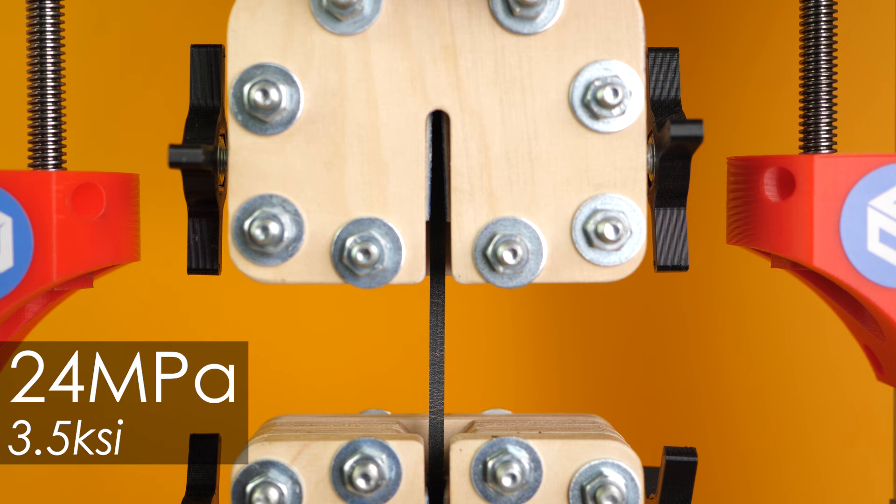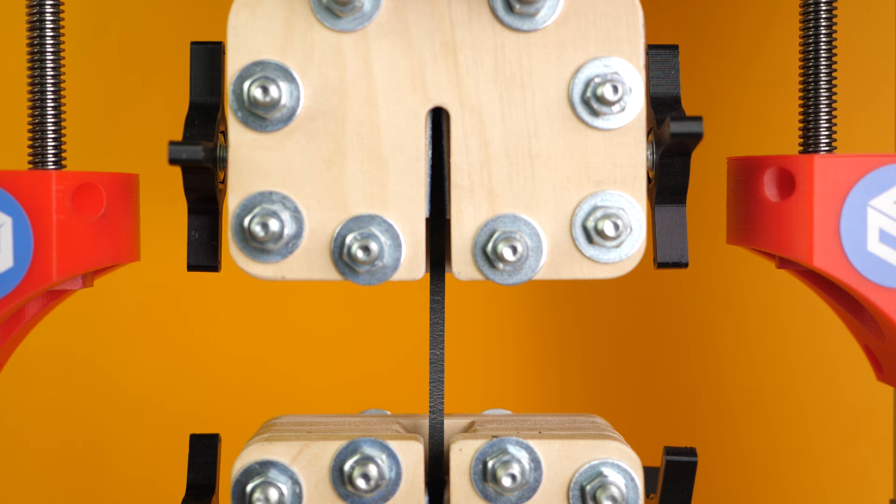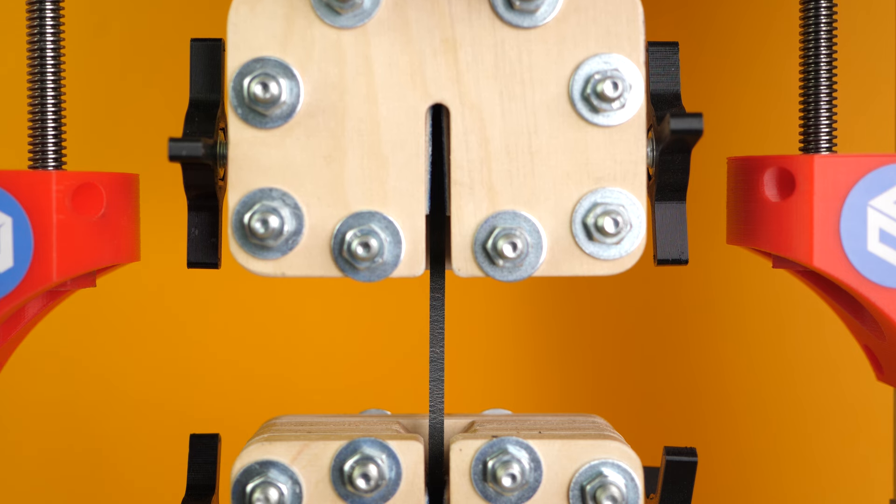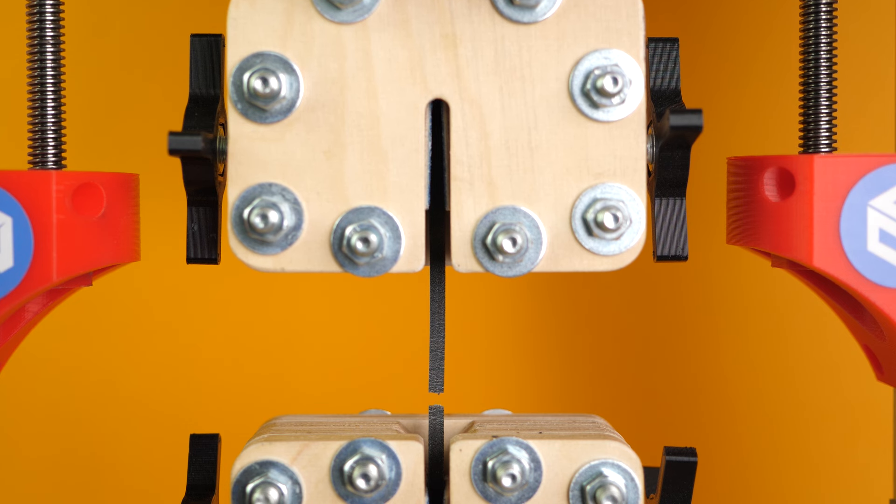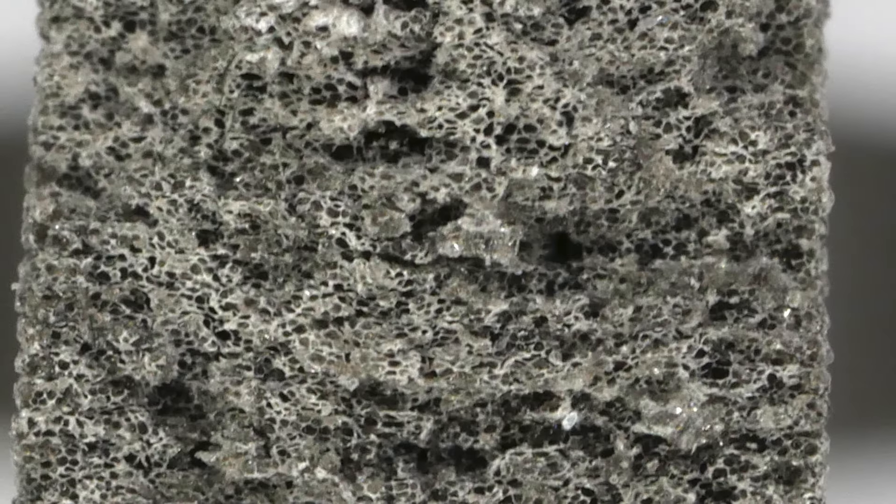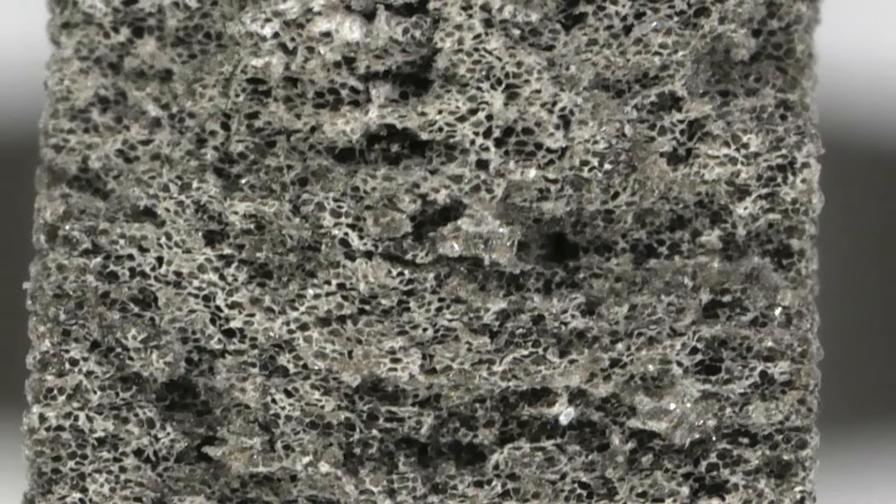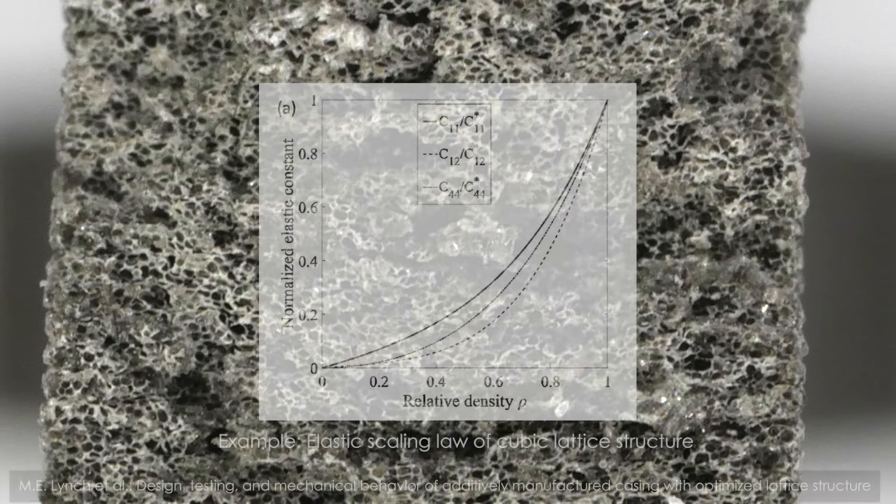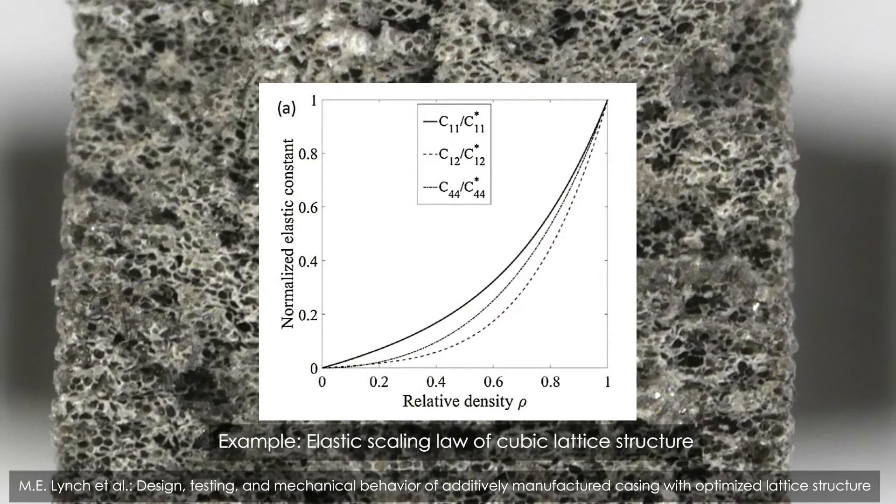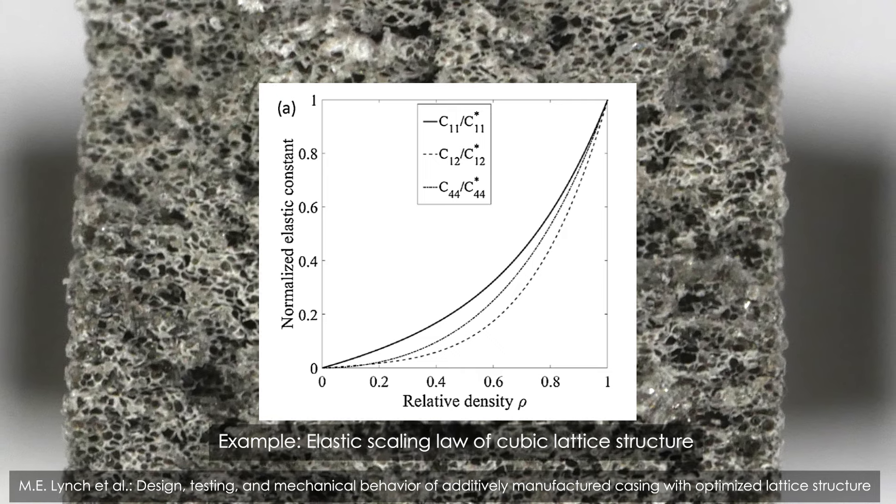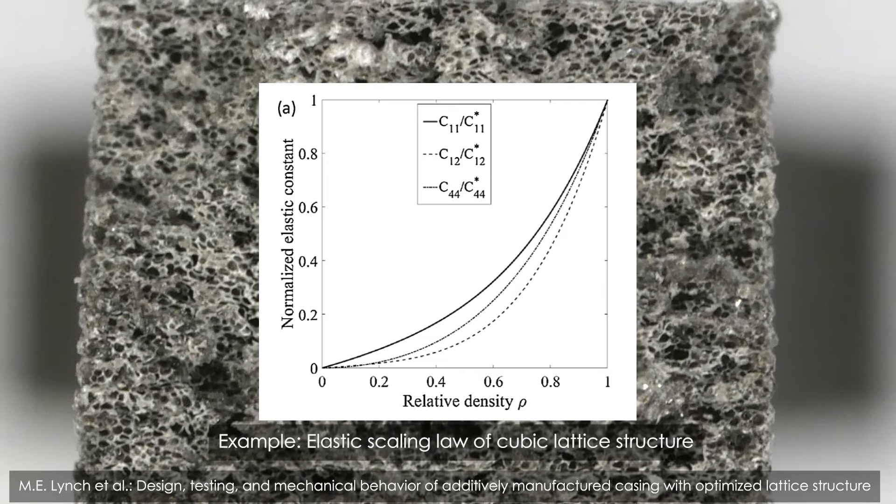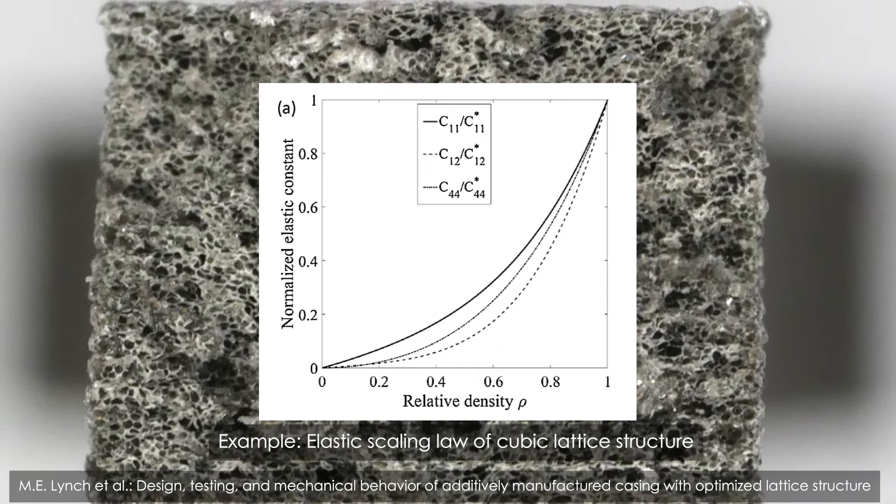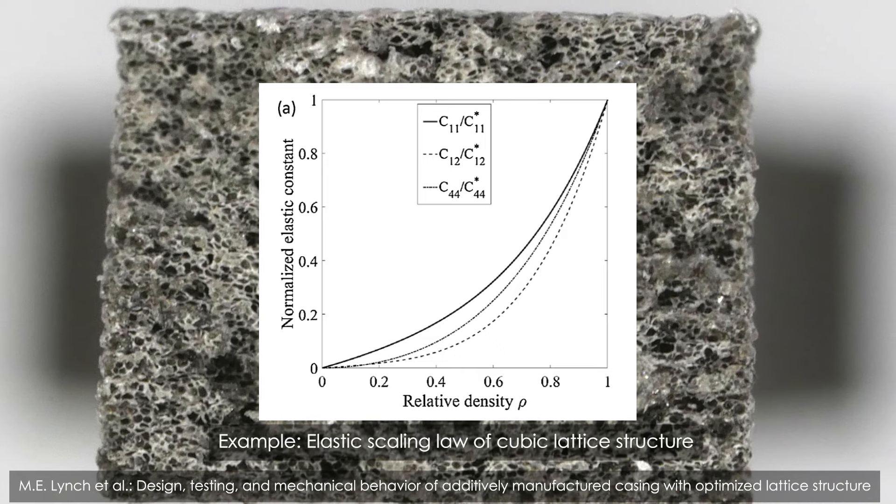The foam parts at 225 degrees Celsius were able to bear roughly half of the load and failed on average at 24MPa which is, considering the density of 67%, a little bit low. So the strength and density don't seem to be totally proportional but I think the values are still pretty good. This is quite a well-known phenomenon of cellular structures and for example described in the Gibson-Ashby scaling law if you want to do further reading on this topic. The scaling law gives you the relation between density and property and is usually not linear.